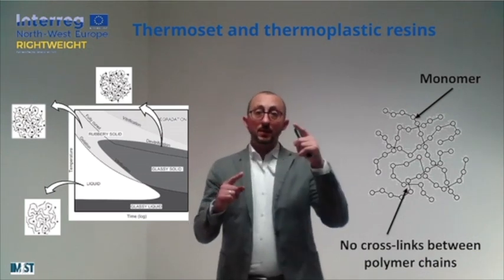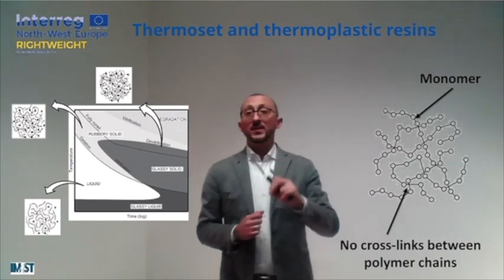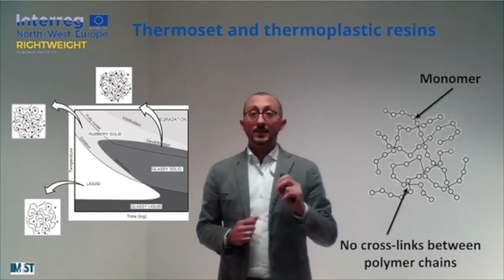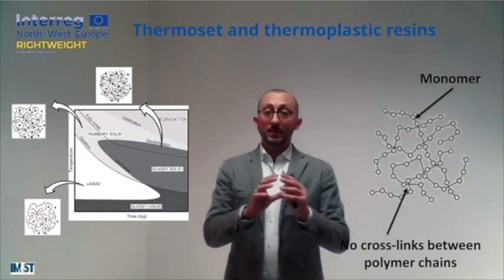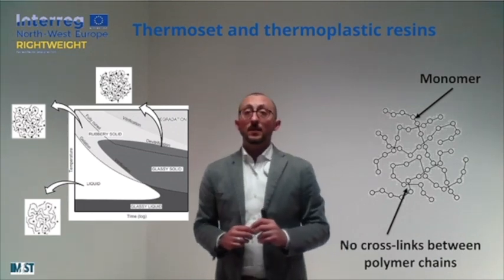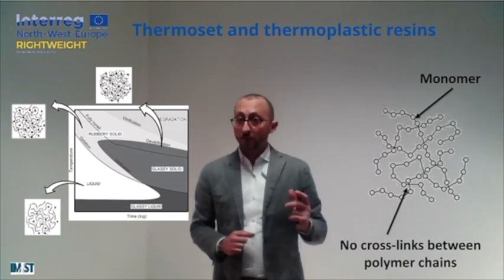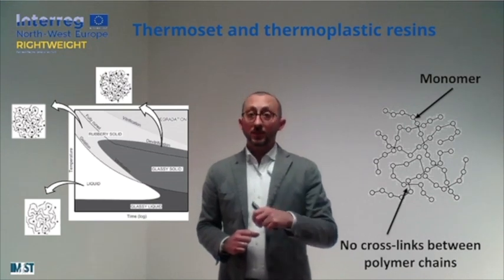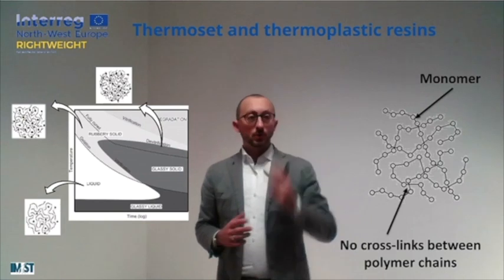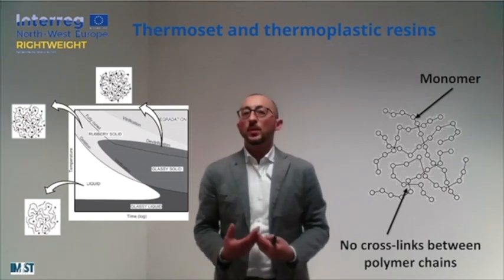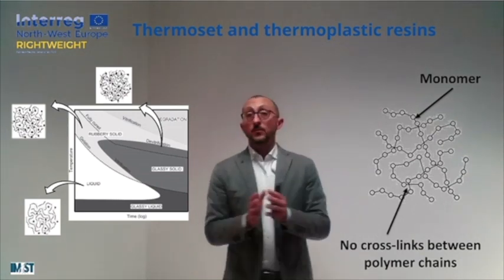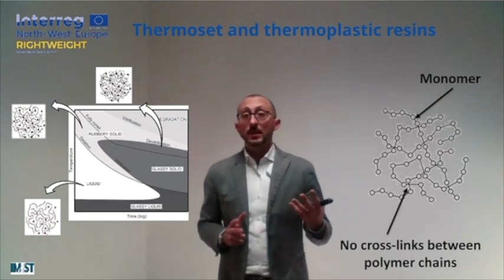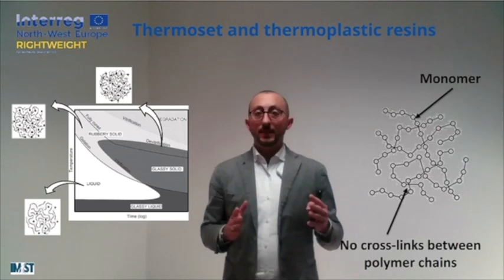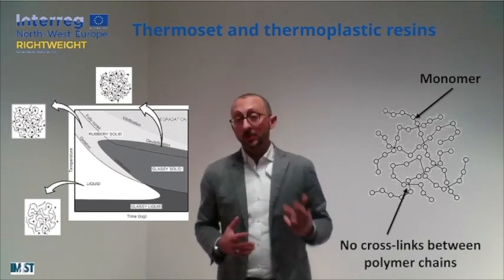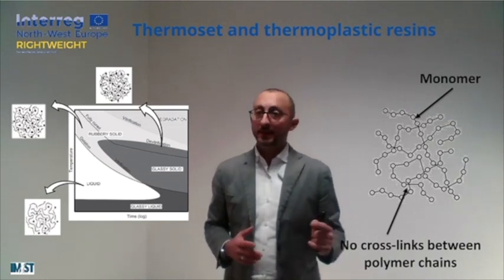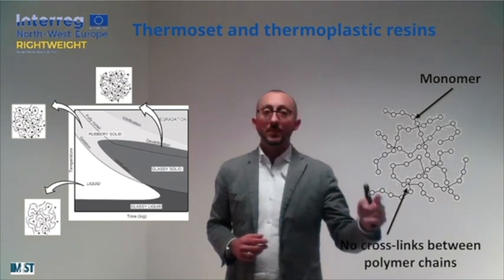0 means the beginning of our reaction, and 1 means 100% of the reaction already completed. And moving from 0 to 1, there is a very important value of the degree of cure corresponding to a fundamental transition from the liquid phase to the rubbery phase. This transition is happening at a precise value of the degree of cure that is specific to each resin, and it corresponds to the so-called gelation. After gelation, our material will not be liquid anymore, will not be able to flow and wet our fibers. So if we want to achieve a proper impregnation using a thermoset material, this step should be completely achieved before the gelation. The gelation transition is a one-way transition, meaning that after moving from liquid state to rubbery state, we cannot go back.